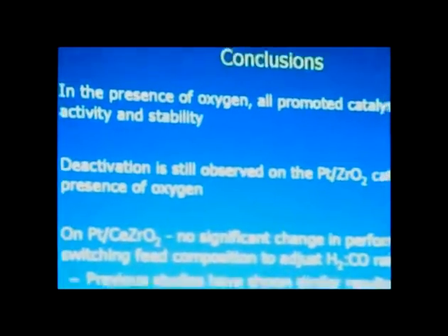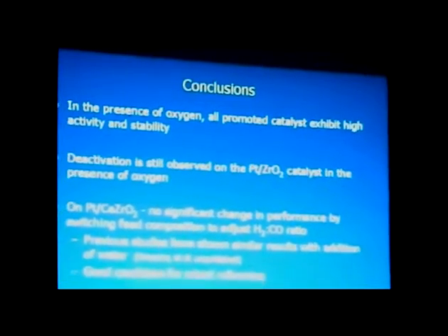In the presence of oxygen, all the promoted catalysts exhibit high activity and stability, whereas deactivation is still observed on the platinum zirconia materials. And on the platinum ceria zirconia, we see no significant change by switching the feeds. And previous studies, unpublished studies, have shown that you can see similar effects with water, so that this is a good candidate for mixed reforming.